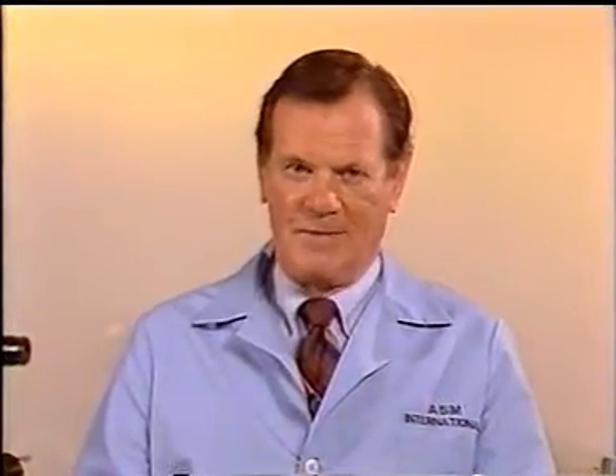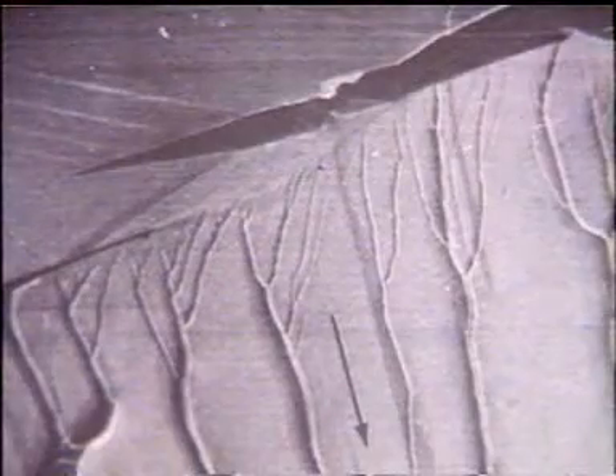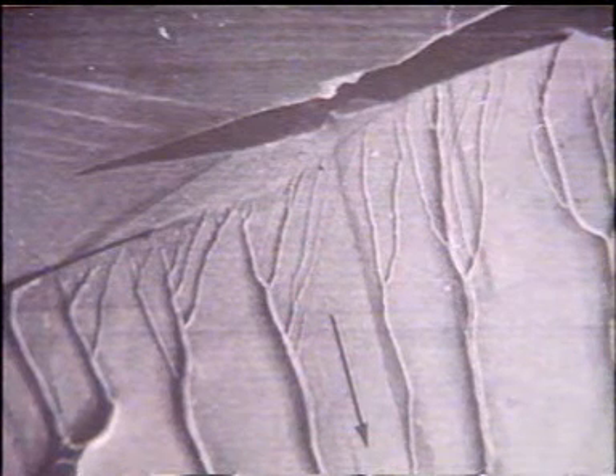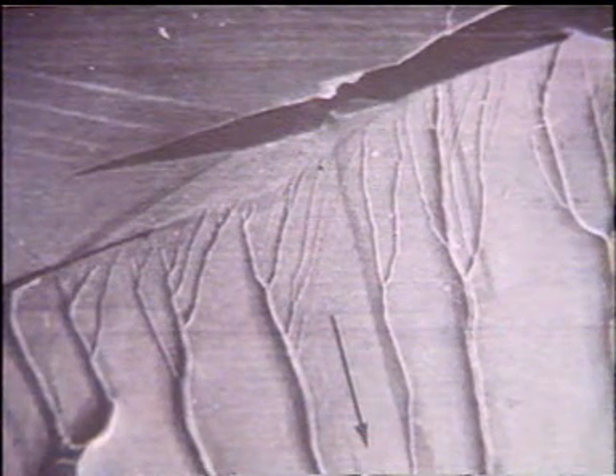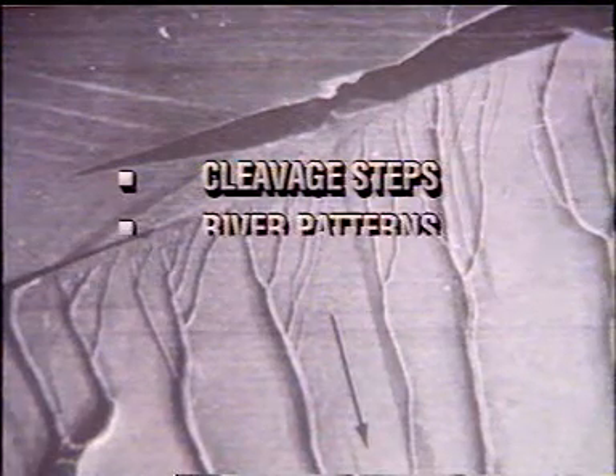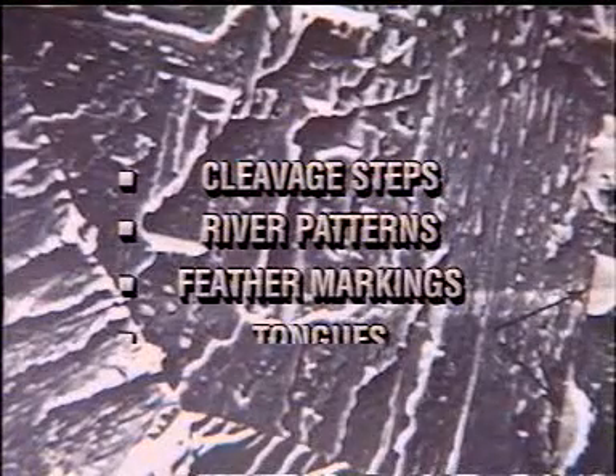Theoretically, a cleavage fracture, that is a brittle fracture, should have perfectly matching faces. On a macroscopic scale, the surface should be completely flat and featureless. However, engineering alloys are polycrystalline, composed of many crystals or grains. They contain grain and subgrain boundaries, inclusions, dislocations, and other imperfections that affect a propagating cleavage fracture, so that true featureless cleavage is never observed. These imperfections and changes in crystal lattice orientation produce distinct cleavage fracture surface features. They are seen as cleavage steps, river patterns, feather markings, and tongues.